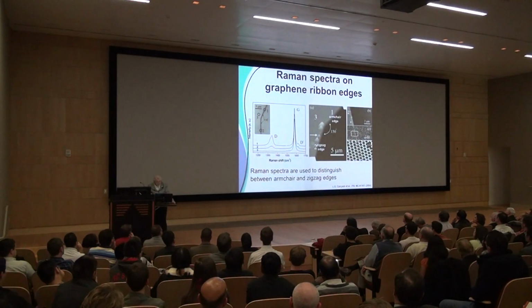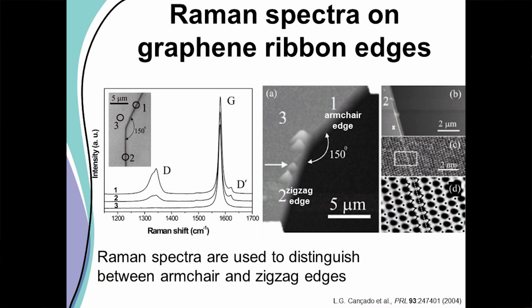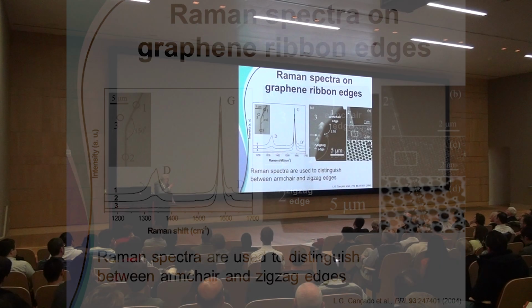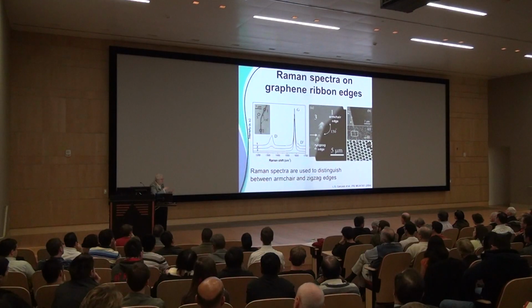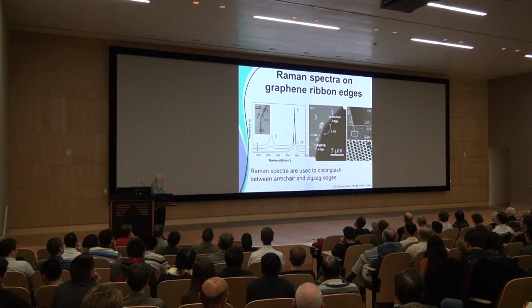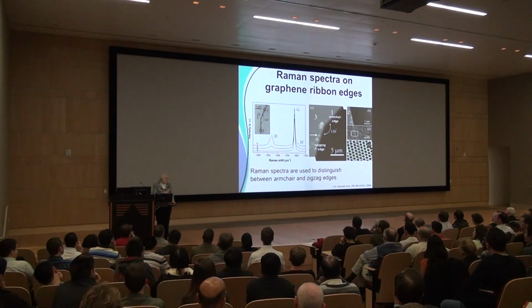We use this to do some spectroscopy and transport measurements, and just to show you that we can tell with a laser. The laser has a wavelength of about a micron, roughly. And we're looking at edges here where you can see the atoms. We get information about what's happening at the atomic scale, even though we're looking with a probe that's very big. That's because if you understand the physics, when we look at the zigzag edge, we're looking for this high density of states. And when we look at the armchair edge, we're looking to see if they're semiconducting or metallic. They have different spectra, but they would have different transport properties too. So all of these things go together.